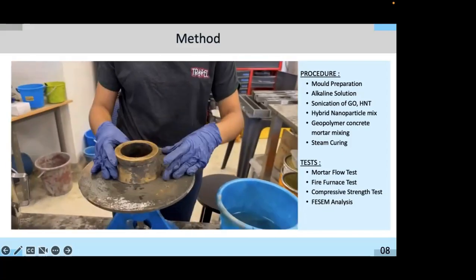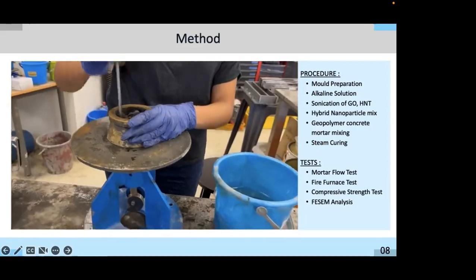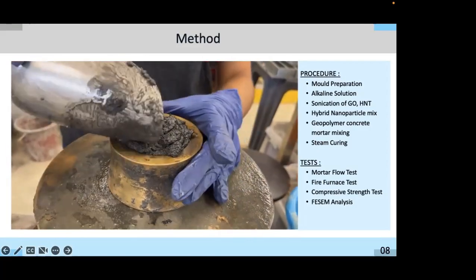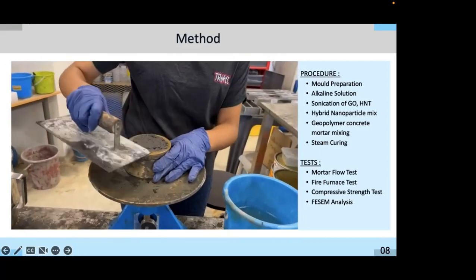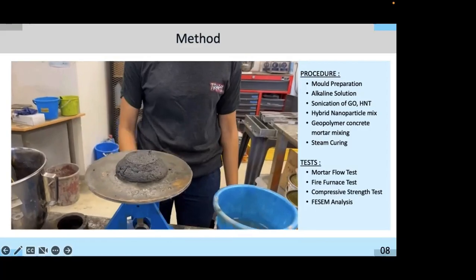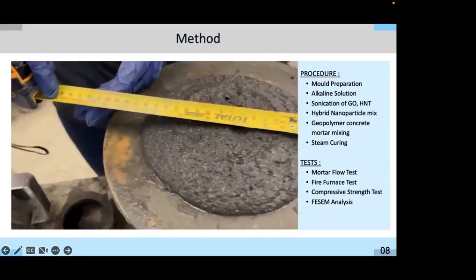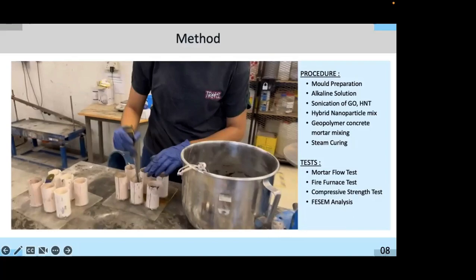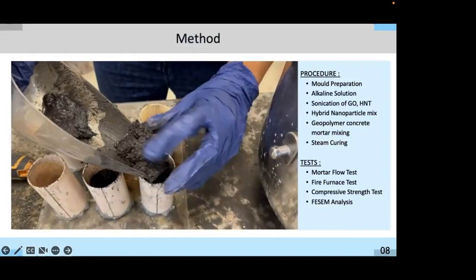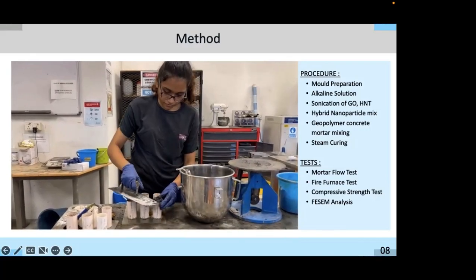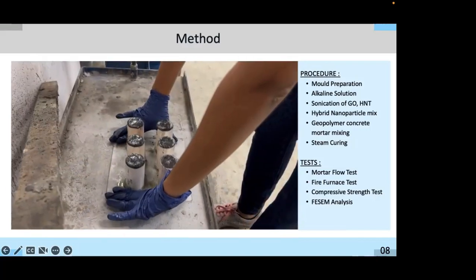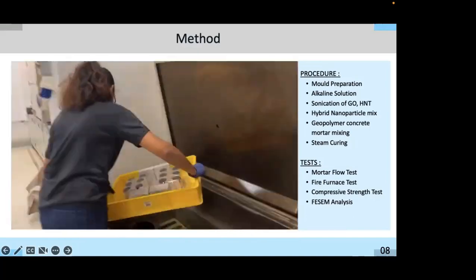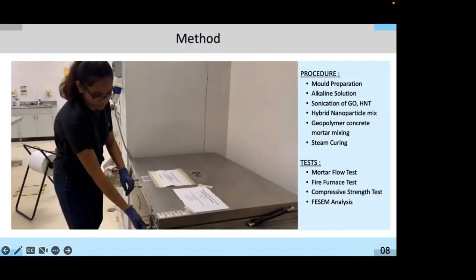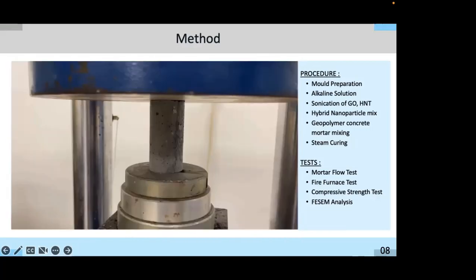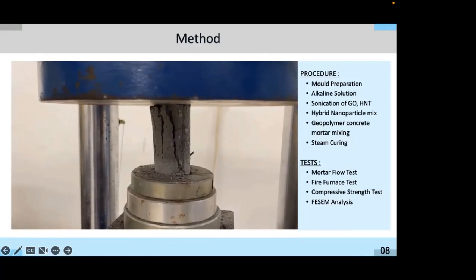As you can see on the surface, it's not much different. Several tests have been done, seeing how it behaves in terms of workability. Then after these tests have been conducted, we've gone ahead to move on to casting the samples. There is some curing that is required for these samples. You can see that it's still being prepared, and then after that it's vibrated, so a combination of tamping and a vibrating table for compaction. And you can see here the student is putting it into a curing tank. I think we've gone for 70 degrees Celsius for a period of 24 hours, if I'm not mistaken.